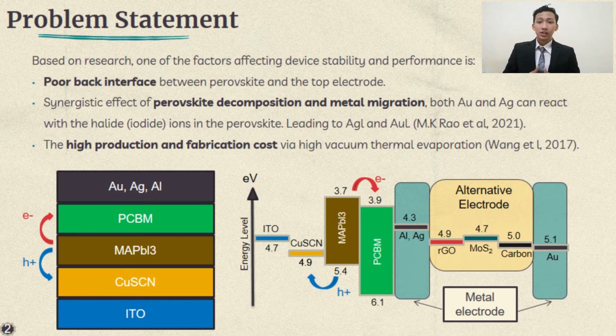As an alternative, carbon material can be used to substitute the use of noble metal, as it permits a comparable energy level and good electrical conductivity. In this research, reduced graphene oxide is proposed to be combined with the transition metal dichalcogenide molybdenum disulfide to form nanohybrid composites that act as an alternative solution-processable top electrode in inverted planar perovskite solar cells.